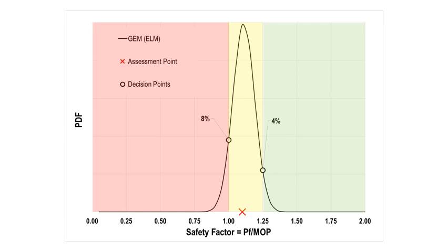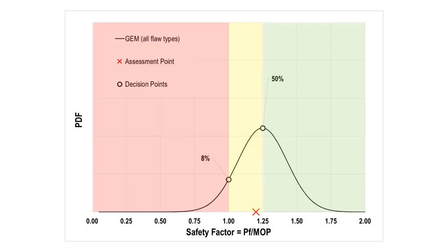Now, this particular version of the model, which I call the ELM, is a level 2 assessment, which means that you have to have the profile. That's not always going to be the case. I do have various other versions of the model. If I lump all of my 300 data together and do a gamma model validation, I find that I've got an accuracy of 1.04, and I've got a standard deviation of 18%. And that's how that would look here.